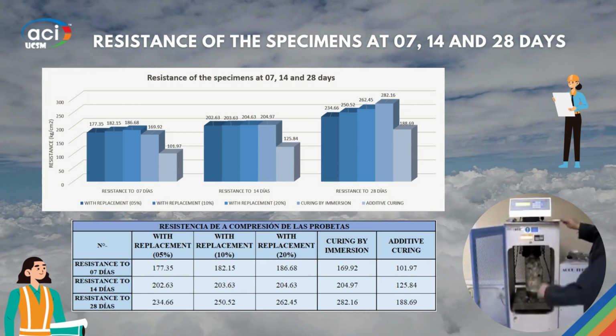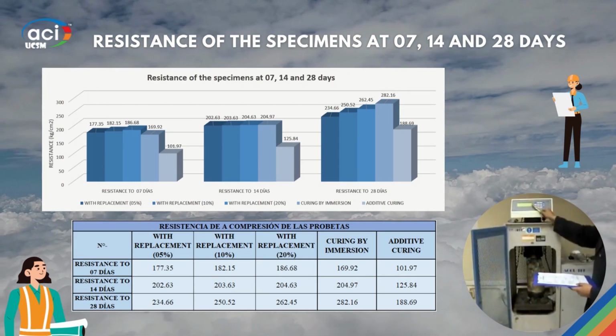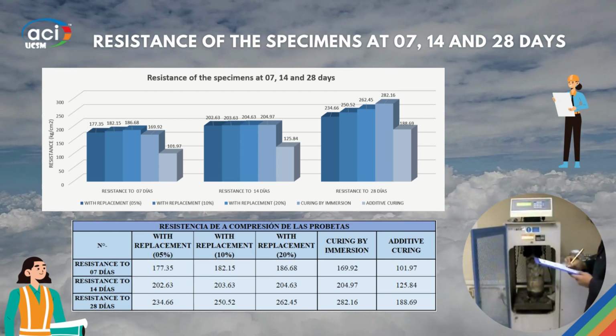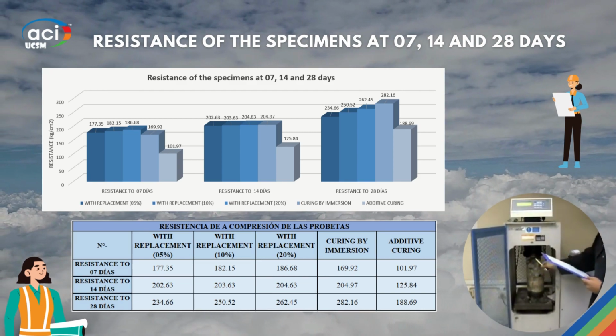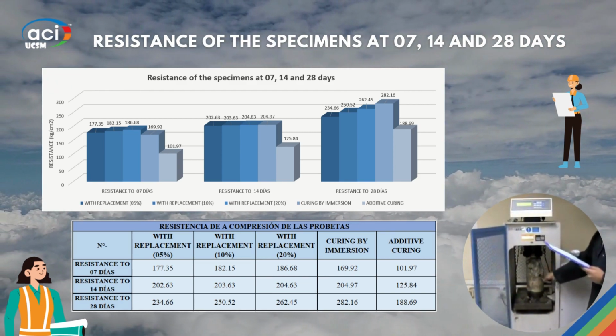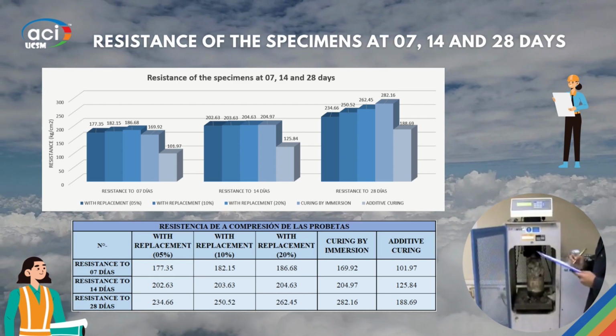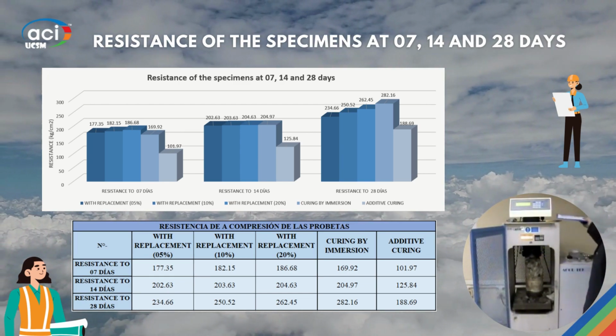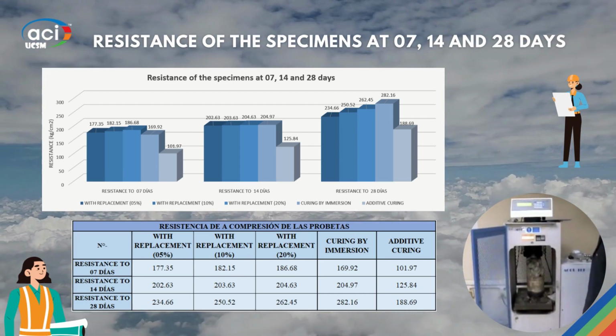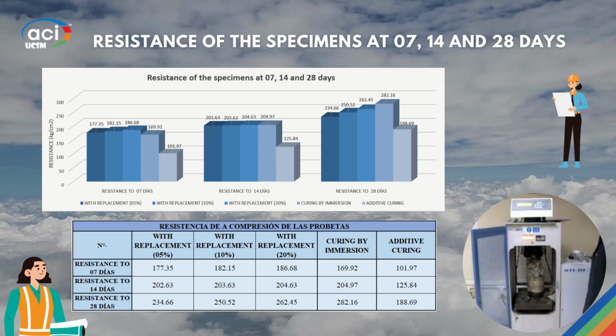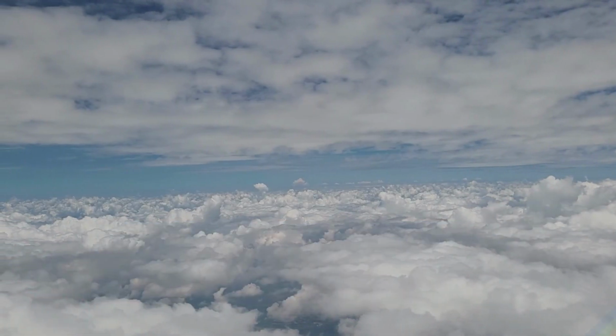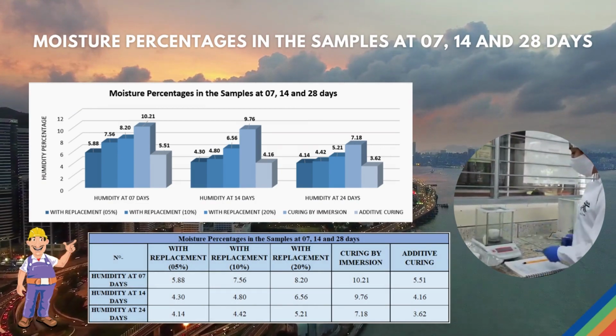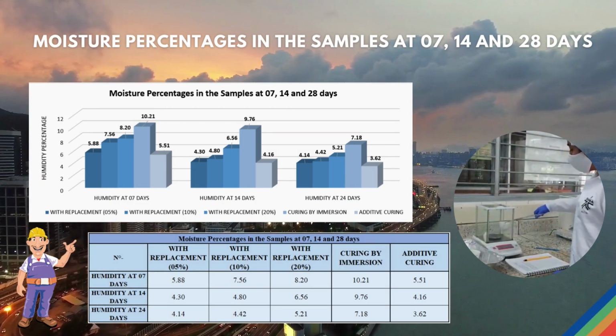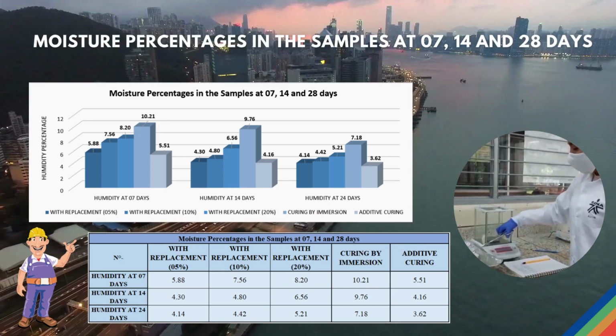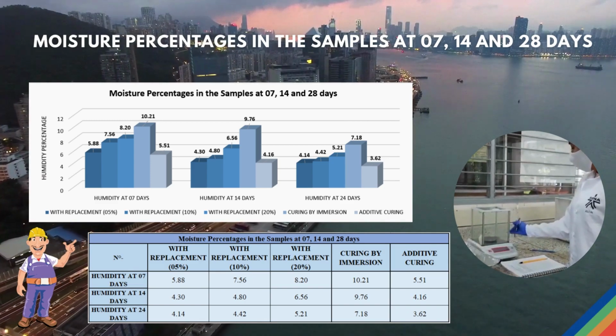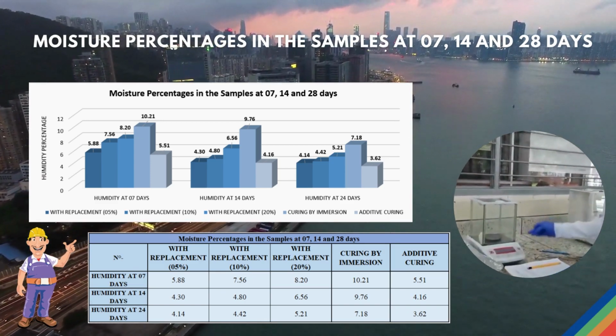As can be seen, the internal curing through the use of saturated crushed clay is superior at 7 days. However, at 14 and 28 days, the curing by immersion is superior to all others, followed by the curing with replacement of 20%, 10%, and 5%. As can be seen, curing by immersion turns out to be the most beneficial because it gives us higher resistances. And what is sought on site is that the resistances on site are as close to those obtained in the laboratory. In a very similar way to the results of the compressive strength, it can be observed that immersion curing is a curing that provides more water to concrete, followed by curing with partial replacement of the aggregate by crushed clay in 20%, 10%, and 5%.